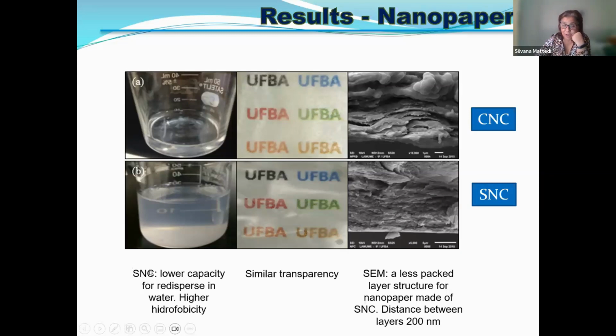So the spherical cellulose has an interesting characteristic. Although it has a lower capacity to redisperse in water because of its higher hydrophobicity, they have similar transparency, and a less packed layer structure for the nanopaper made of the spherical nanocellulose. So the distance between the layers here is 200 nanometers.